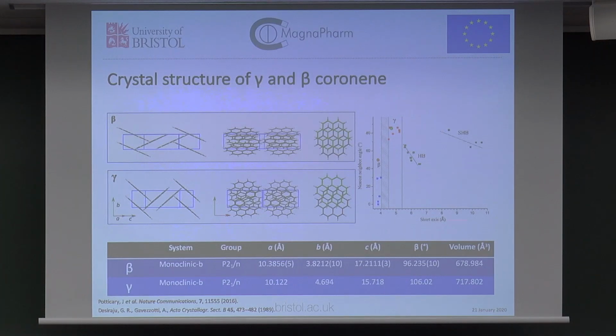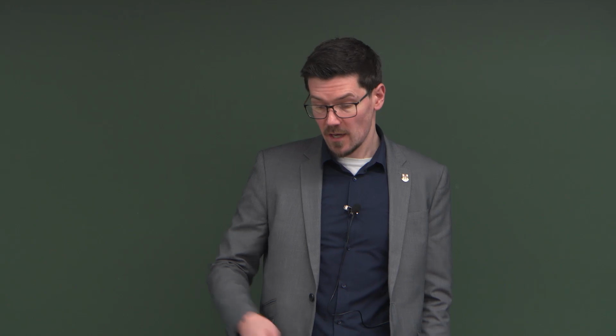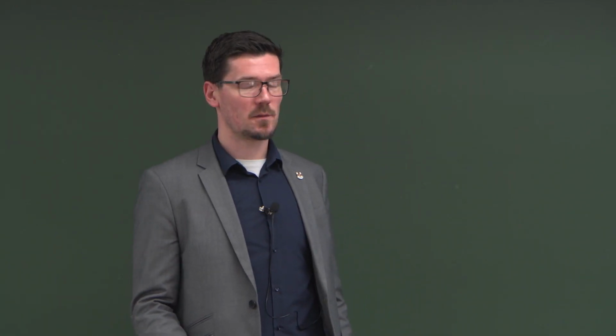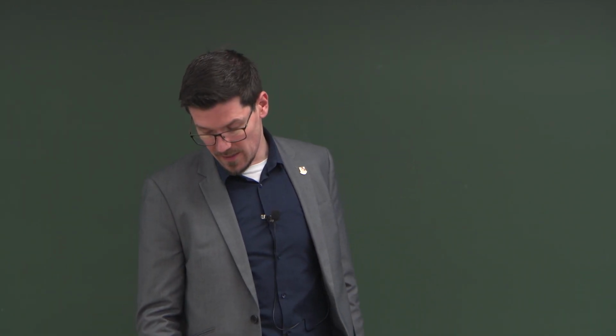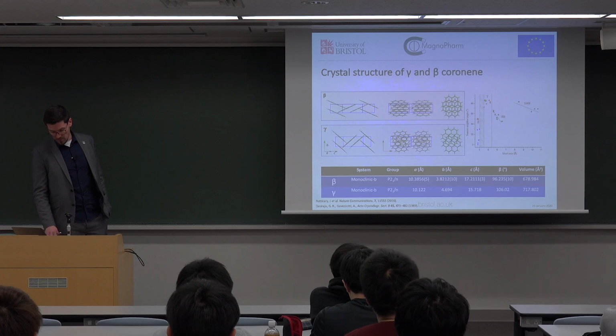You can see the unit cell parameters down here. The B-axis is significantly shorter. So a polymorph that no one knew existed, we'd found by growing these crystals under magnetic fields. Were we the first to do polymorph selectivity?